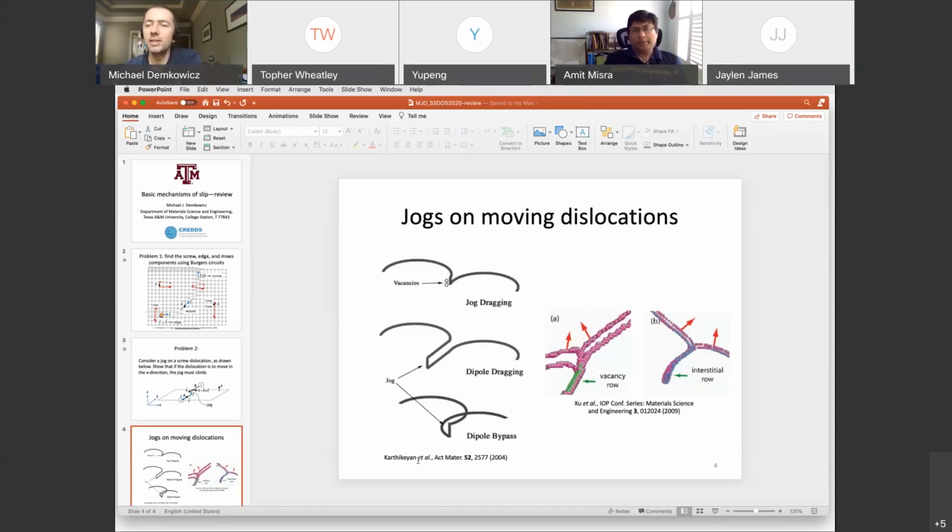Okay, good. Right. So if you were under regular low strain rate conditions, then the likelihood of jog drag is low because diffusion processes are generally fast enough to make these jogs climb. So, generation of copious quantities of point defects by jog drag is one of the phenomena that occur under relatively high strain rates and high stresses.